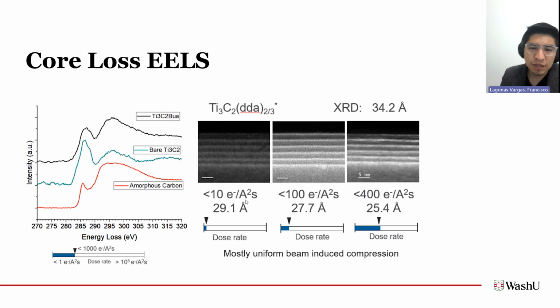So at 10 electrons per angstrom squared, we can just barely resolve the spacing between these MXene sheets. Definitely can't do atomic resolution, but we can get some statistics about the basal plane spacing. And you can see that as we start increasing the amount of electrons that we pump into the sample, we can correlate this with a decrease in the magnitude of the basal plane spacing. So we go from 29.1 down to 25.4. You'll notice that this effect happens really uniformly across the sample. So it's not like we would see very localized swelling of these layers.